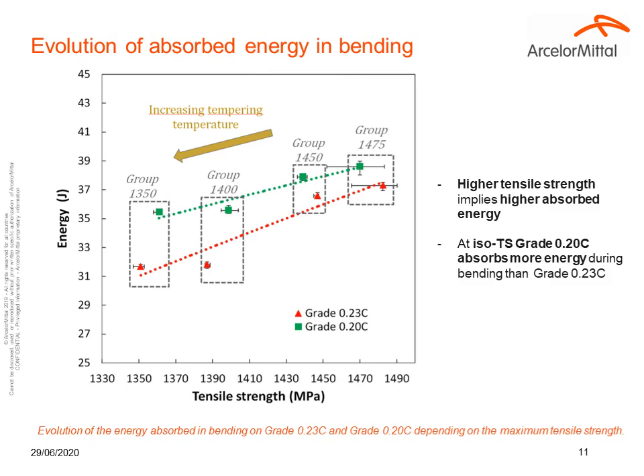The first evidence to notice is that a higher tensile strength implies a higher absorbed energy. This is because tensile strength has a strong impact on the absorbed energy in bending. But for the four different groups at the same tensile strength, the grade 0.20 absorbed more energy during bending than grade 0.23. The absorbed energy is not just linked to the tensile strength, but also to the chemistry and other microstructural evolution of the martensite induced by the tempering.